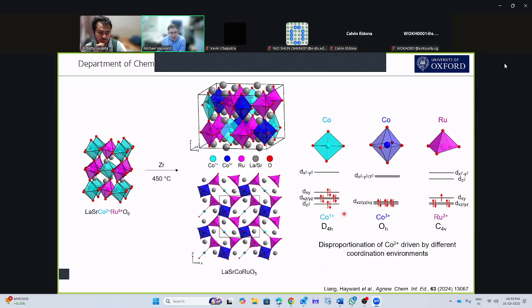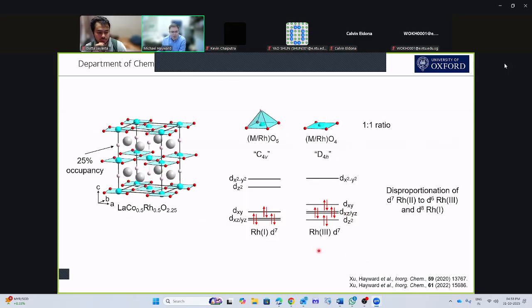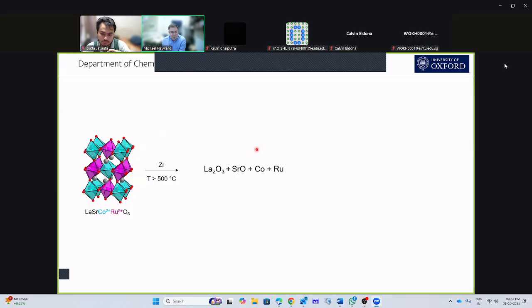And I think this is the first example of such a disproportionation, because the disproportionation of the heavier homologs below cobalt, so rhodium and iridium, are very standard. So we already made a compound which formally is rhodium 2, but is actually a 1,3 disproportionated product driven by the same reaction. Okay, so we can make an O5 phase, but can we make an O4 phase?